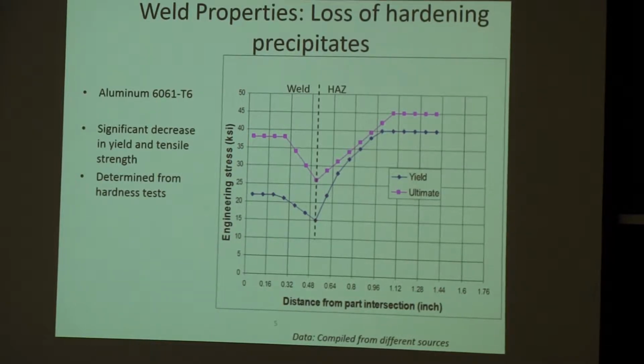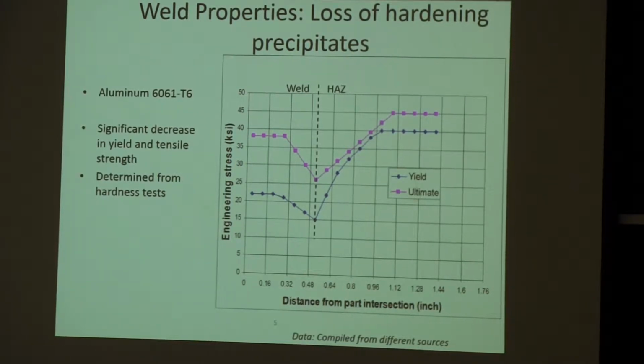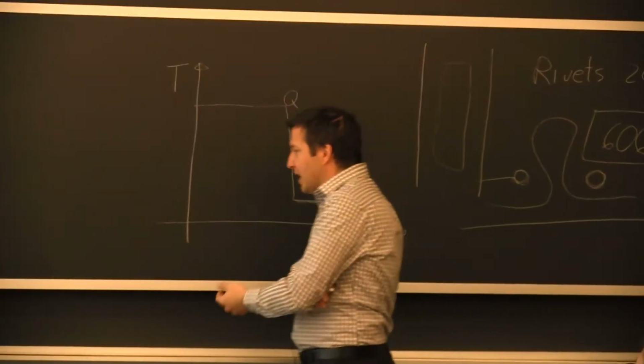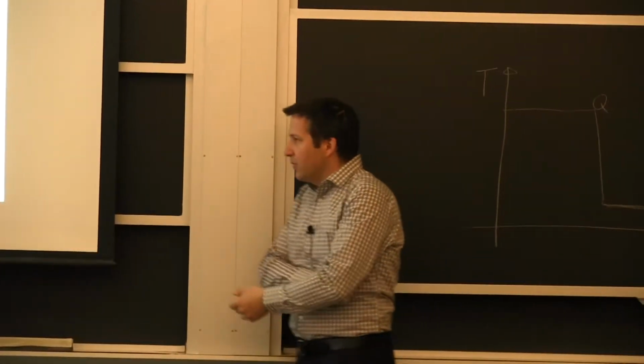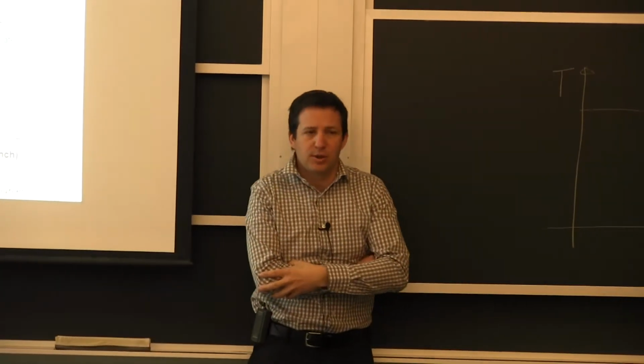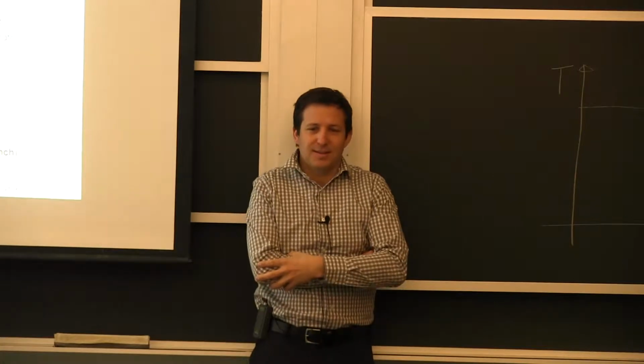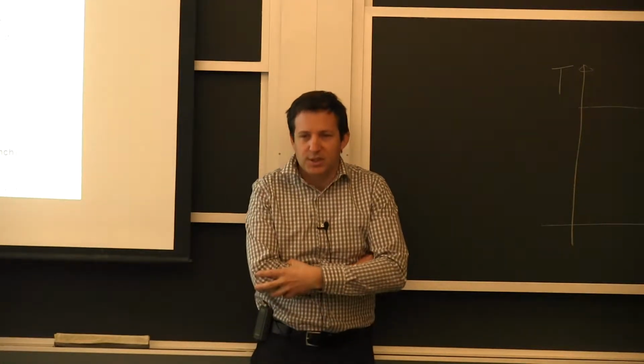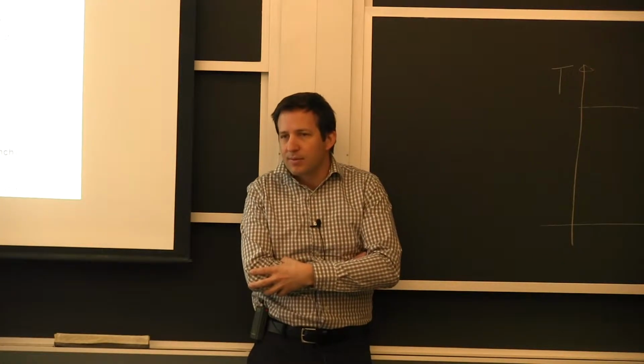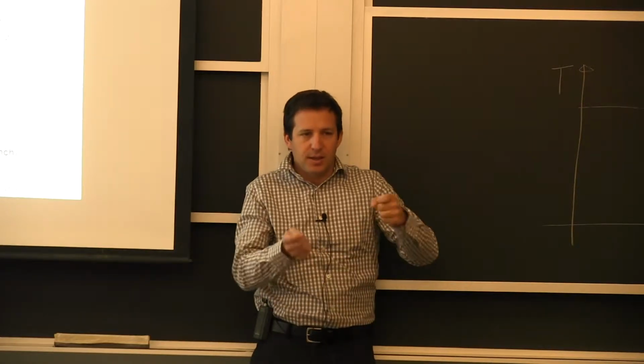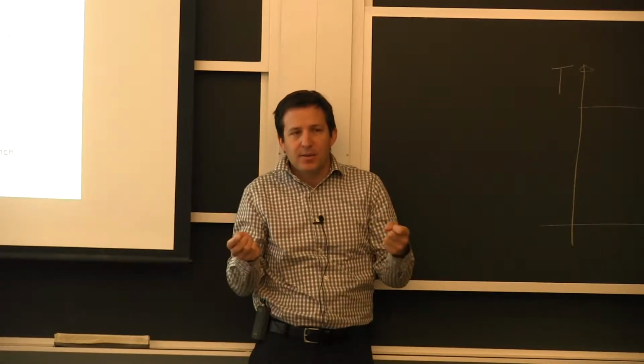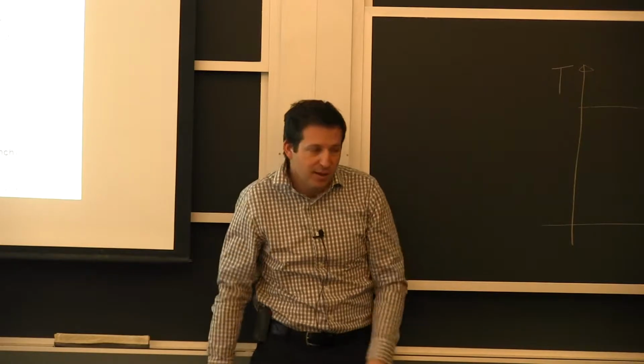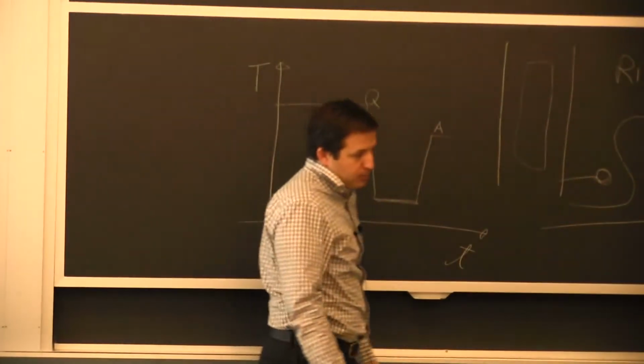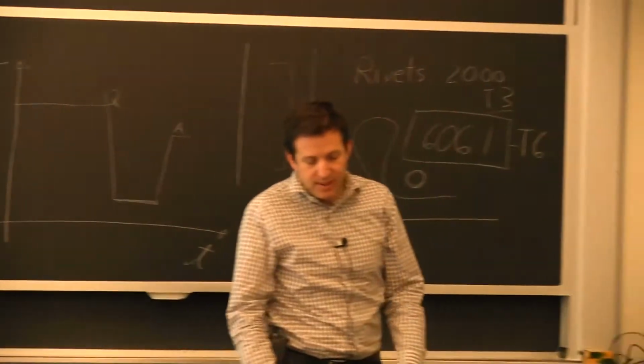So depending on what you're designing for, and if you're looking at fatigue, that's the reason why, in terms of aluminum alloys, you have to take an additional factor of safety if you're going to weld aluminum. It's not becoming brittle. It's just becoming really, really soft in the heat affected zone. And therefore, if you have cyclic deformation, fatigue, you'll have a chance to form cracks at a lower load.